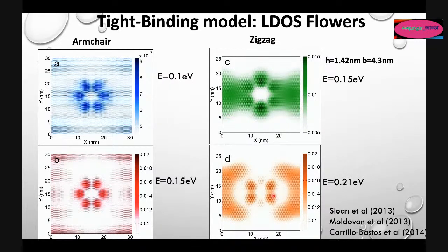So what this is saying is that for a wide range of energies, here we are going through a range of 100 millielectron volts to 150 millielectron volts. And you see that in this region of energy, here is even wider, we see a charge accumulation in particular regions of the sample, and charge depletion. The density of states, the number of electrons in the white areas has been depleted, is 0, because these electrons have moved to these regions. And these regions have the size of the bubble diameter, basically. They have the size, roughly, of the width of the Gaussian at half height.